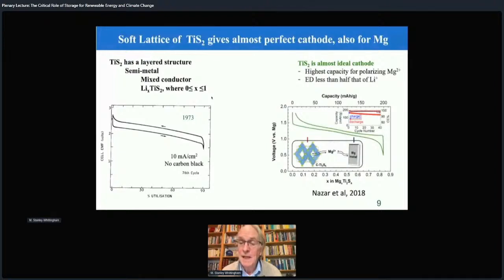So Linda Nazar in Canada found out that magnesium would go in and out of this material very readily. And you can see the sloping behavior is almost identical to lithium. The big difference is it's about 1 volt lower. It's operated at an elevated temperature as compared with room temperature for the lithium case, and the current density is much lower. So TiS2 is a model compound, lithium preferred one because the lithium energy density is twice that of magnesium. So magnesium, good model area, but not realistic for commercial application.